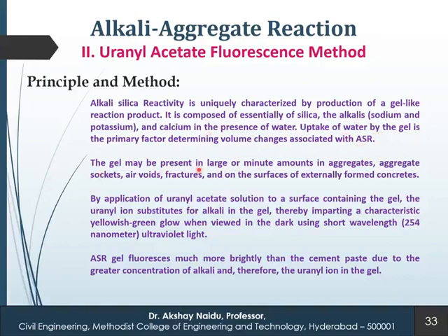The gel may be present in large or minute amounts in aggregates, aggregate sockets, air voids, fractures, and on the surface of externally formed concrete. By application of uranyl acetate solution to the surface containing the gel, the uranyl ions substitute for the alkali in the gel, thereby imparting a characteristic yellowish green glow when viewed in the dark using short wavelength ultraviolet light.